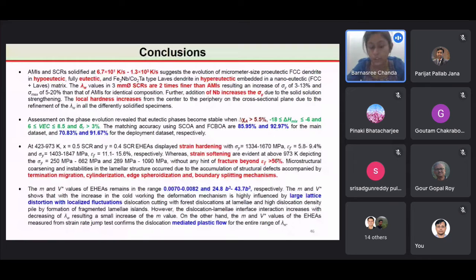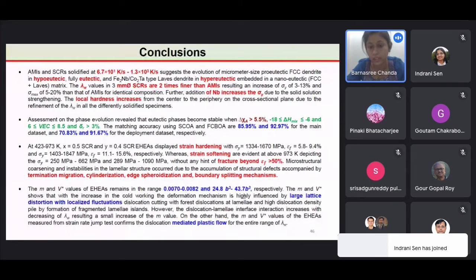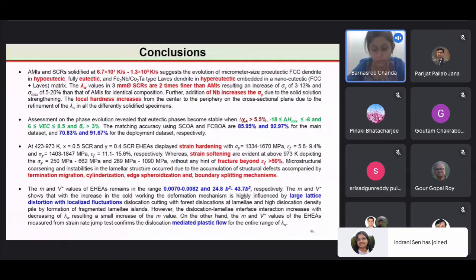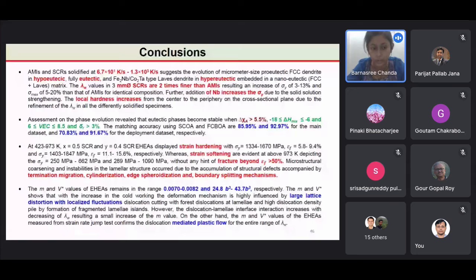High temperature deformation shows that at intermediate temperature, strain hardening plays the dominant role, whereas at higher temperature, dynamic recrystallization, that is dynamic softening, plays the major role. Also, various coarsening mechanisms can be seen, that is the termination migration, cylindrization, edge spheroidization, and boundary splitting.